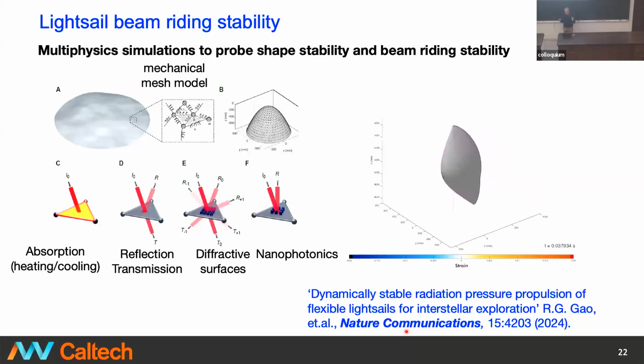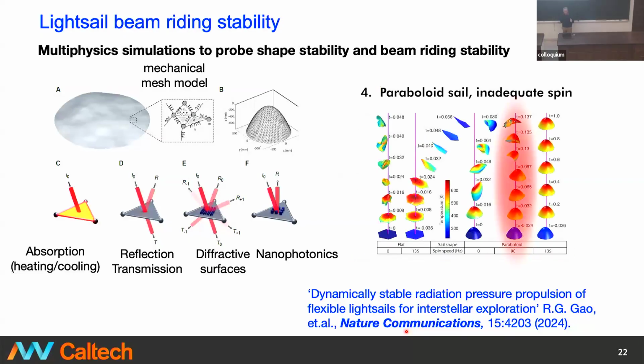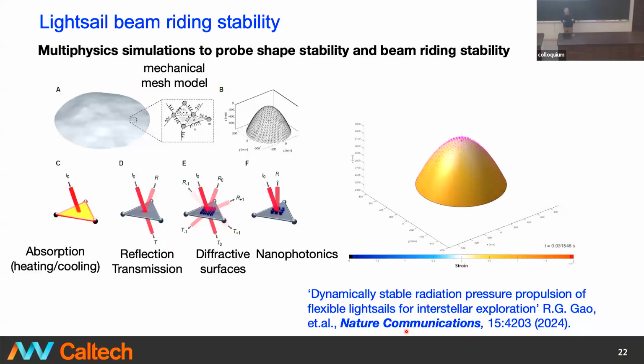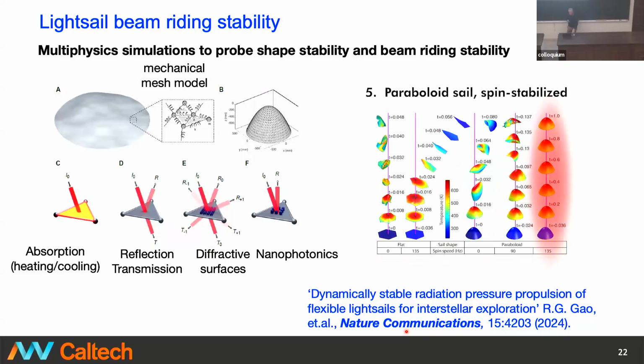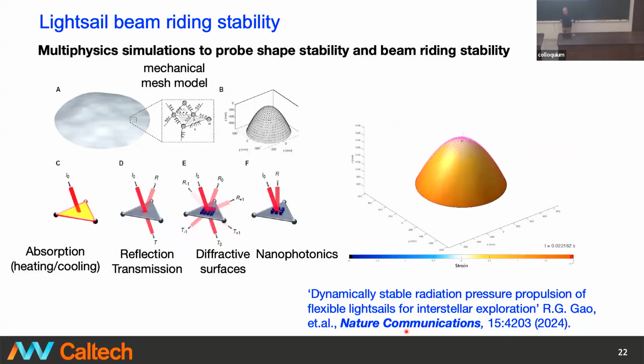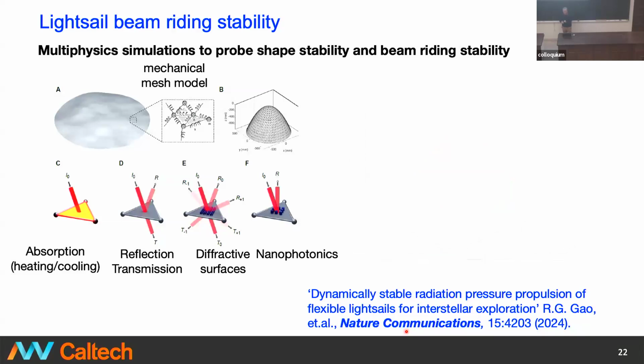So if you use something like a parabola, you can show that a parabola, if it could maintain its shape, would have beam riding stability, but a thin membrane parabola, even if you could imagine making it, can undergo deformation unless you rotate it. If you rotate it, the stability gets a little bit better, but ultimately this one wasn't rotated fast enough, so it meets the same fate. If you rotate fast enough, you can stabilize this membrane. Essentially what you're doing is trying to rotate at a speed such that the tensile forces, stresses on the material don't exceed the tensile yield strength of your material. So typically if you have structures that are tens of square meters in size, if they're rotating something like 10 to 100 RPM, that is below that tensile limit.